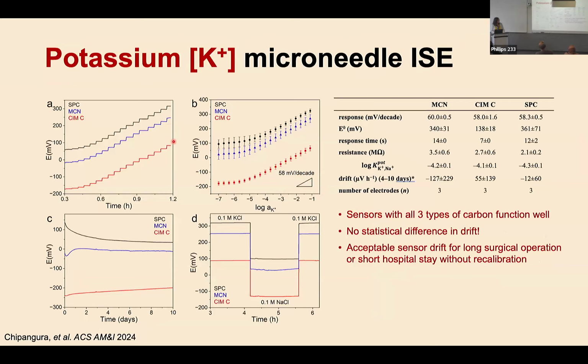And so we get this really nice, what's called Nernstian response, where the slope of this line as a function of the concentration is exactly what we expect to see for this system. So we were able to show that this worked for potassium. It also works for pH. And we're investigating this now for other applications, including wound healing as well.